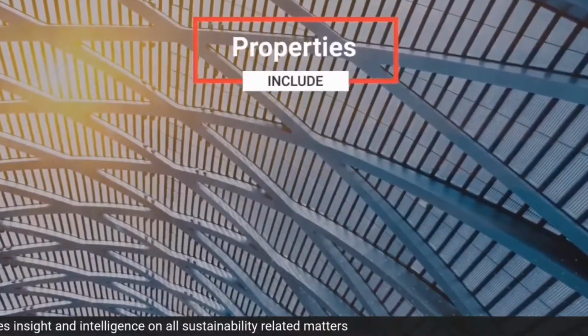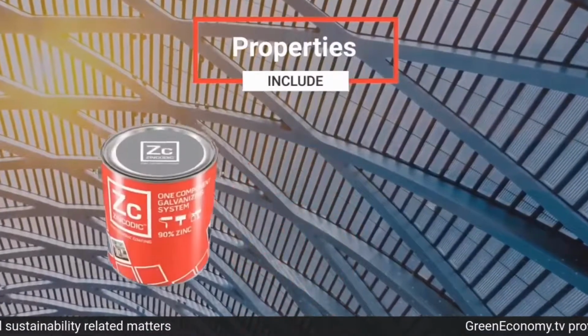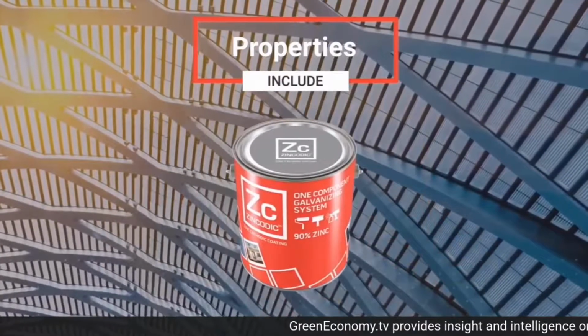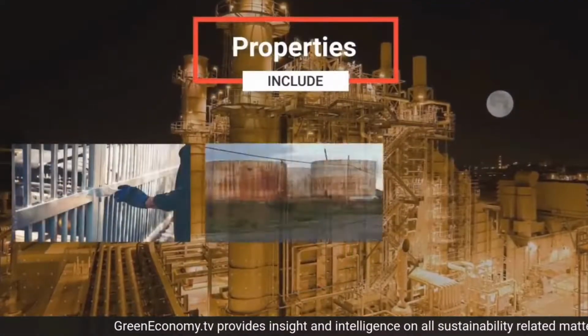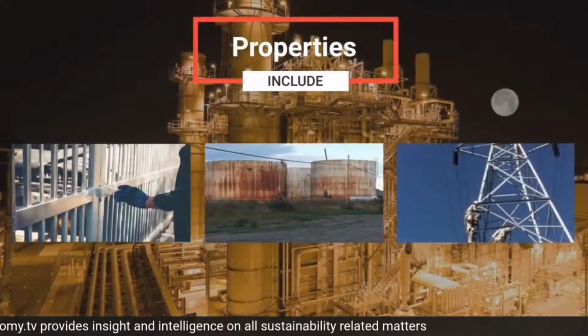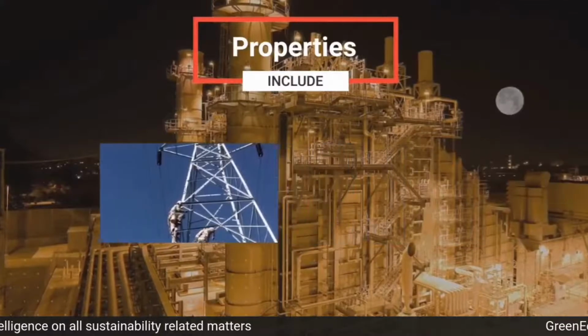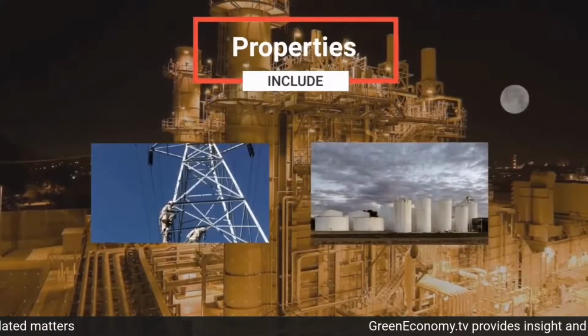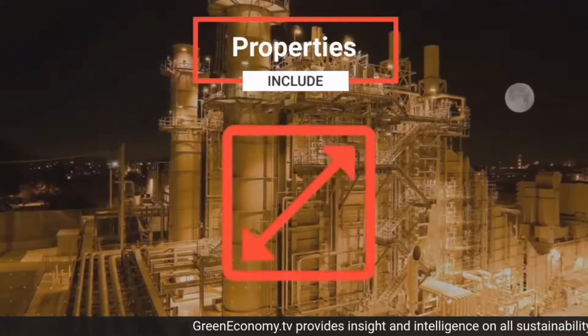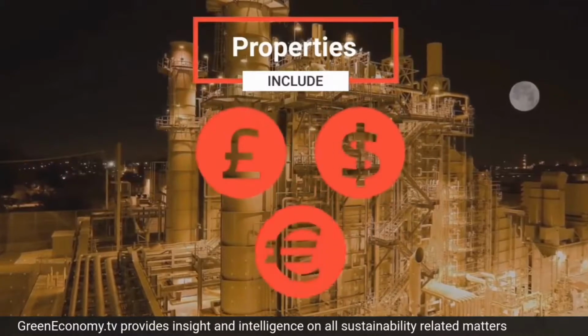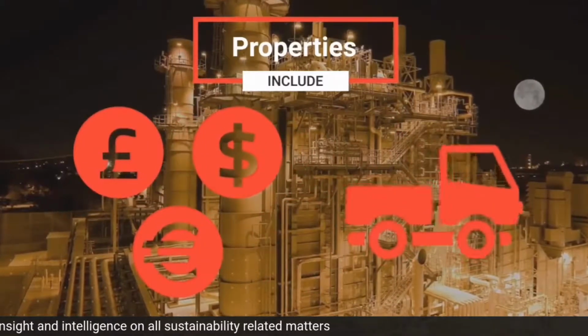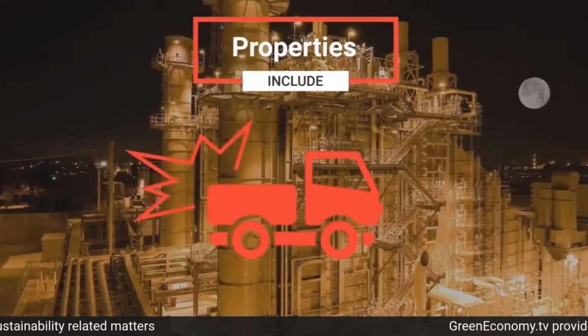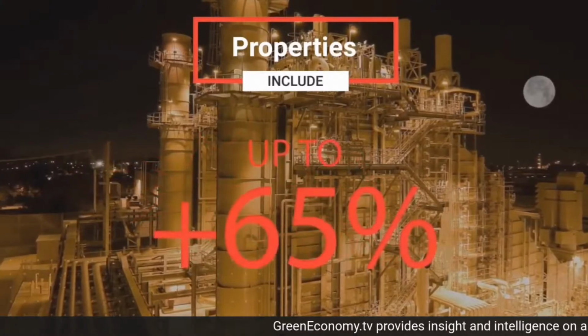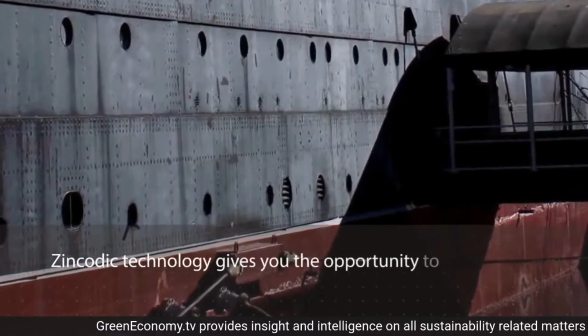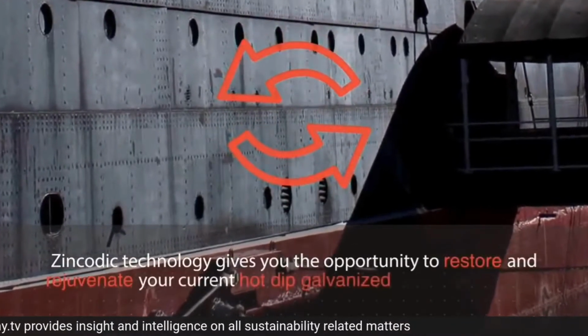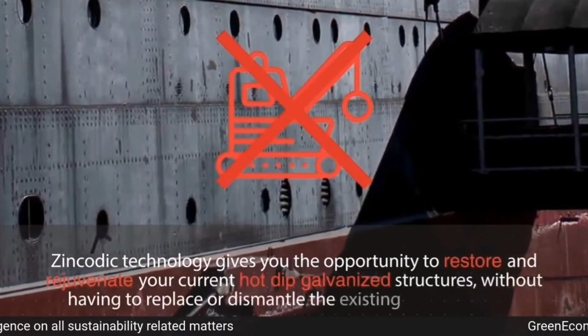Some of the many benefits or properties include ready to use, single component, an alternative to hot-dip galvanizing. Zincodic technology can be applied to a new substrate, an existing rusted substrate, as well as to existing hot-dip galvanizing. Can restore cathodic protection of an existing galvanized coating or an existing Zincodic coating. Can be applied to any substrate, regardless of dimensions or shape. Can be applied in situ, providing cost-effective saving on transportation costs from your facility to hot-dip facilities, as well as saving on transport damage. Savings of up to 65% can be achieved. Zincodic technology gives you the opportunity to restore and rejuvenate your current hot-dip galvanized structures without having to replace or dismantle the existing structure itself.